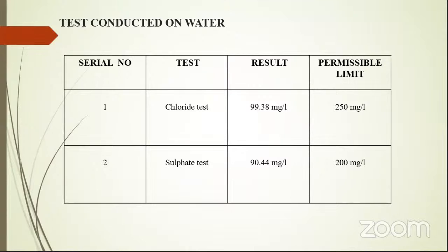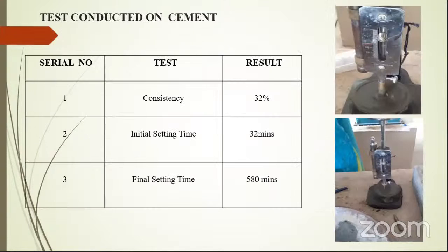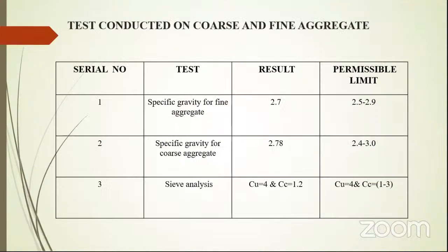Test conducted on water, the permissible limit for the chloride test is about 250 milligram per liter, and for the sulfate test we get about 90.44 milligram per liter. The permissible limit is 200 milligram per liter. For the consistency, the result is about 32%, and initial setting time is 32 minutes. Final setting time is about 580 minutes.